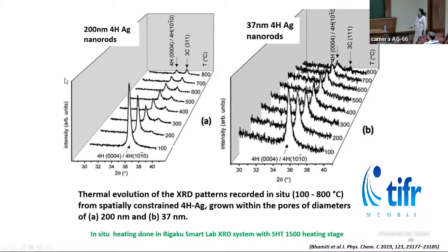So this is the in situ XRD done on two different diameters of 4H silver nanowire. This is the data of 200 nanometer diameter wires. Here we can see that at 200, this is the peak corresponding to a 3C phase, and this is the peak corresponding to a 4H phase.